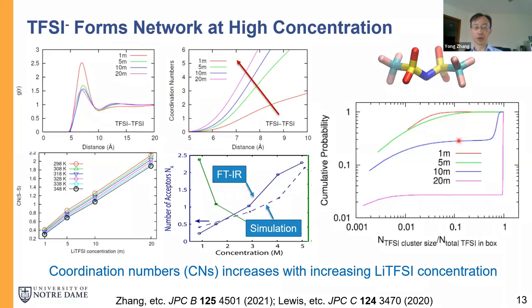Things totally changed at 10 molal. We have about 30% of LiTFSI that still exist as a small cluster, monomer, dimer, all those things. Now we see a sharp increase here, which means 70% of LiTFSI are connected to each other. So this is like a huge, big network or cluster.